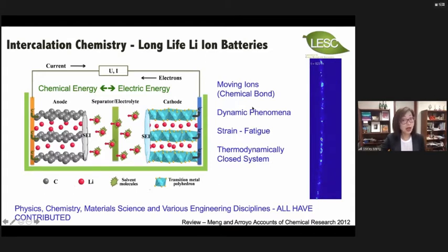During this dynamic phenomenon, one has to realize that even for intercalation chemistry, there are a few percent of volume changes happening. And think about your battery having to go through 1,000 or 3,000 times of those volume changes. A good analogy is an airplane that has to take off and land because of the pressure difference between the atmosphere and high altitude. The materials go through a strain event where we eventually experience fatigue and develop defects, and that's how the battery material eventually starts to fail or degrade.